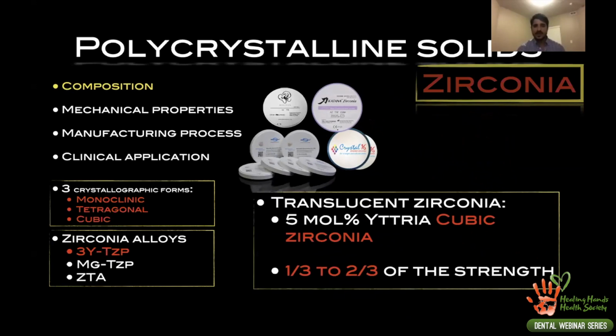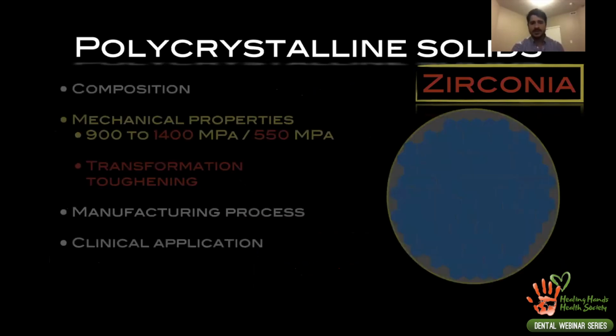That being said, recently, and when I say recently, it's recent scientifically, which means 5 to 10 years ago, the manufacturers developed what we call translucent zirconia. What they did was increase the amount of yttria within the zirconia to close to 5 to 8%. And instead of stabilizing the zirconia in the tetragonal phase, now you stabilize it in the cubic phase. However, they lost some of the mechanical properties, and the flexural strength of the material dropped from 1/3 to 2/3 of the conventional zirconia. And you understand why right now.